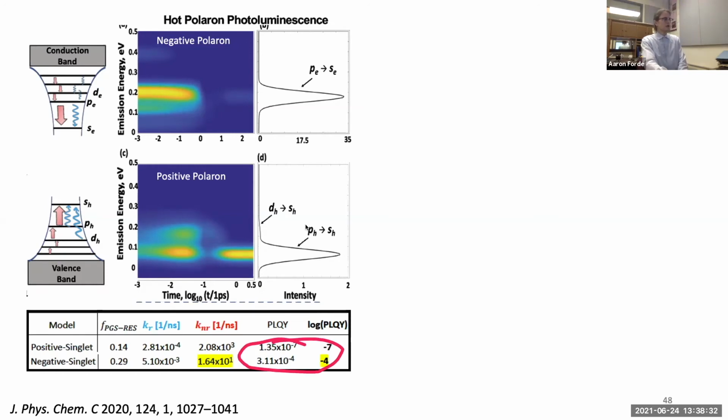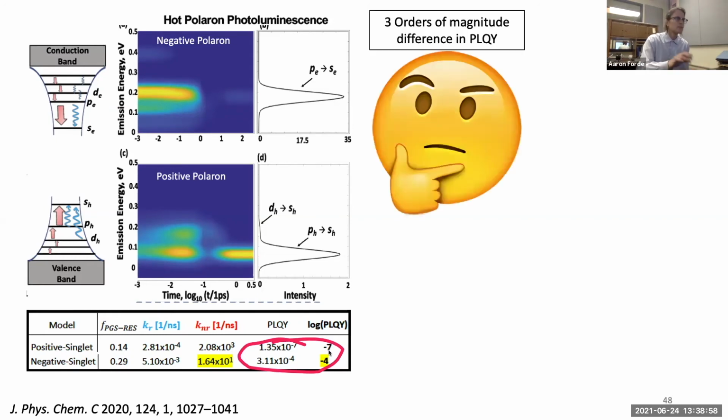And so we compute intensities, but we compute rate constants, so we can try to calculate theoretical yields for these luminescents. And disappointingly, they're fairly low. So like 1% would have been something that could have been promising, but we see much, much lower. But the interesting feature is that there's 3 orders of magnitude difference between their photoluminescence quantum yields, which should raise some question marks about what could give such a big discrepancy.